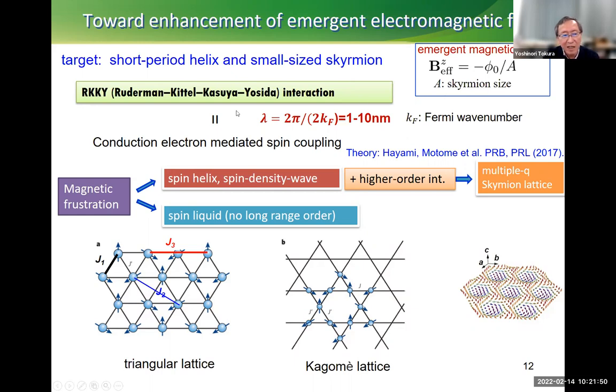So in order to realize such a short period helix and also small size skyrmions, we may use the so-called RKKY interaction. It's a conduction electron mediated spin coupling, moment coupling. And sometimes the interorbital fluctuation plays an important role. But usually the 1/kF is around the 1 to 10 nanometer scale, so that we can expect a very small size of the skyrmion or helix structures.